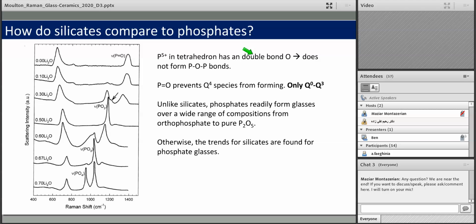And I'll stop on this slide, but there's a lot of similarities between silicates and phosphates. For instance, instead of being 4+, phosphorus is 5+, and as a result of the need for an extra electron here, there is a double bond of the phosphorus to one of the oxygens. And this prevents an extra linking, which means the only difference between phosphates and silicates is that you can't form Q4 species. You only form Q0 to Q3 structures. This is what the Raman spectra on the left-hand side show.